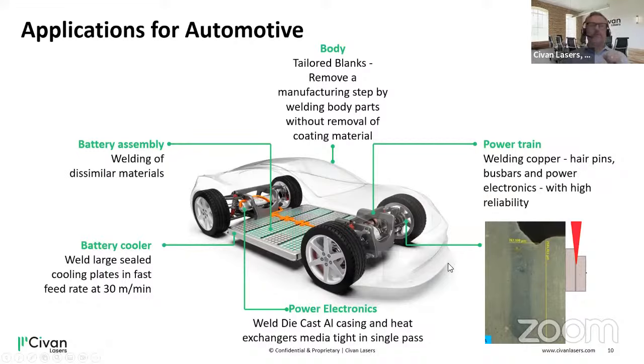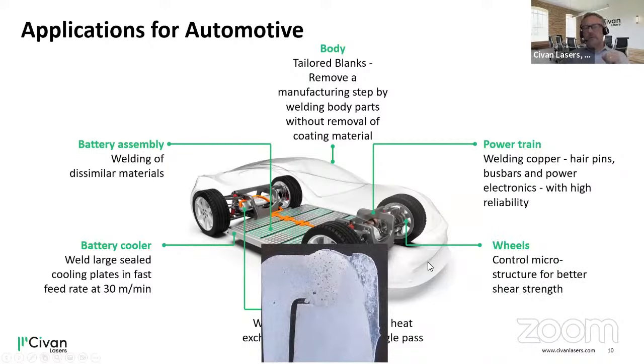Next one, which is I think one of the highlights, is the welding of die-cast aluminum. Die-cast aluminum is a material that's really everywhere. But for example, heat exchangers or the housings of power electronics of the inverters are made from die-cast aluminum. So the problem is they get sealed when everything's built in, and then you want them to be gas and water and liquid sealed. And the problem really is the H2 that's trapped in the material itself. So typically you get a lot of porosity.